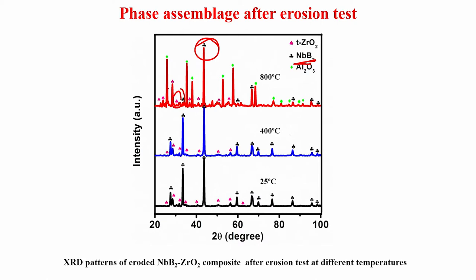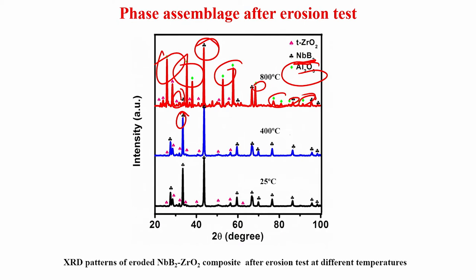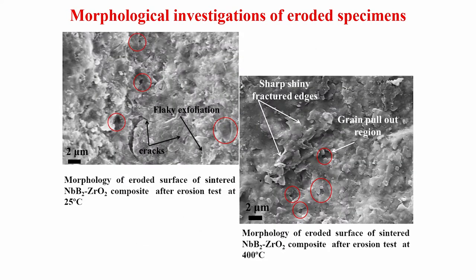In terms of phase assemblage after the erosion test, the niobium boride material at 400°C shows very clear niobium boride peaks with no niobium oxide peaks — so niobium boride is extremely resistant to oxidation. At 800°C you see a lot of alumina particles completely embedded on or covering the surfaces — even after ultrasonic cleaning the alumina particles are embedded very strongly. The tetragonal zirconia peak present in the spark plasma sintered materials comes from the milling media.